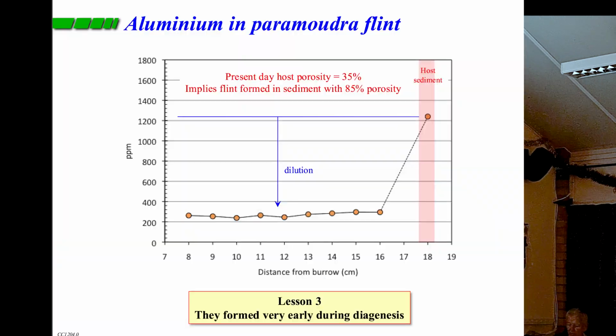And you can see that here. This is actually looking at dilution in the flint samples. Through here is the aluminium content of what's in the host chalk. Aluminium is an essential ingredient of clay minerals. When we come into the flint, we've actually got a lot less aluminium, and that's because it formed before the chalk compacted. So this variation from the host sediment to the flint, this dilution of aluminium or clay minerals, reflects the amount of compaction which has occurred in the flint since it formed.